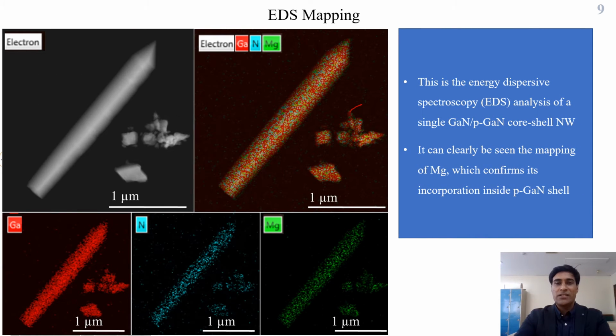And this is the energy dispersive spectroscopy analysis, EDS mapping. We did it to confirm the incorporation of magnesium, because magnesium incorporation is a difficult job using MOCVD. But in this image, which is for magnesium, you can see that magnesium is incorporated.